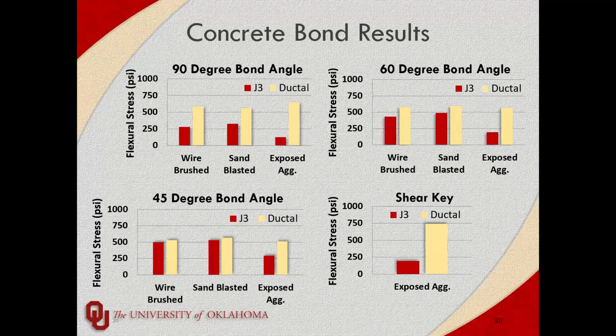But mainly, one thing we observed was all of these mixes have a very low water cement ratio, and J3 seemed to be susceptible to moisture migration at the interface. None of those interfaces were treated with water, they were just dry. We were trying to do a worst case to see what we were working with. And we noticed that it looked like the exposed aggregate interface just seemed to suck the water right out of J3. So it would break at that surface and we would actually see dust right at that interface on the